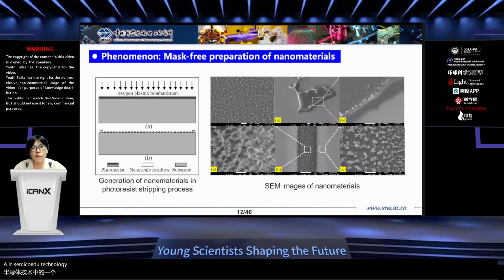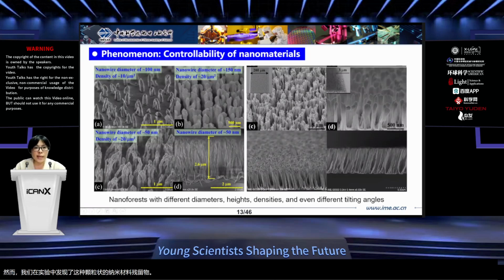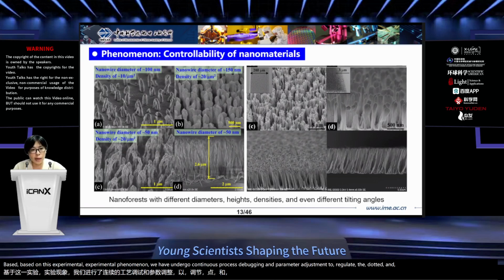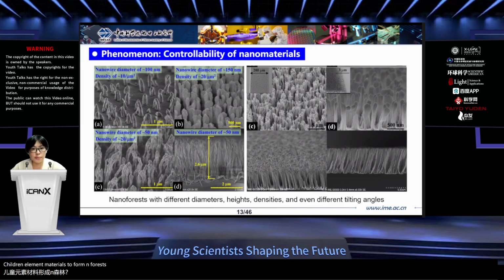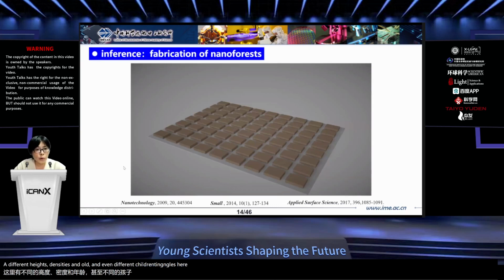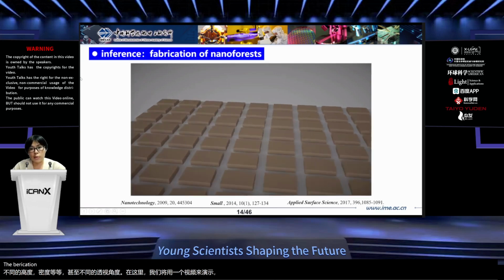In semiconductor technology, photoresist stripping using plasma is a commonly adopted dry process step. Generally, we believe that after a long period of photoresist stripping, the substrate surface should be quite clean. However, we found this kind of dotted and flocculent nanomaterial residues in our experiment. Based on this experimental phenomenon, we have undergone continuous process debugging and parameter adjustment to regulate the dotted and flocculent nanomaterials to form nanoforests. Currently, we have been able to fabricate nanoforests with different diameters, different heights, densities, and even different tilting angles.